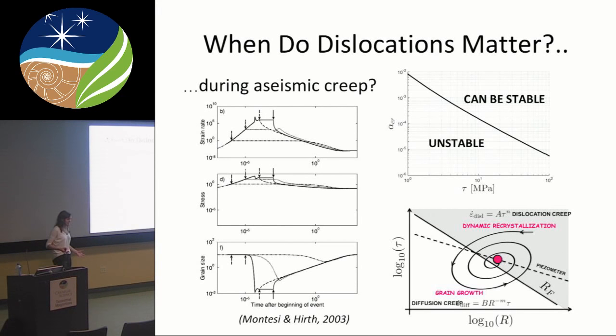So geological settings with this kind of physics could be important is, for example, a case of aseismic creep. So the scenario we're envisioning, if you have a sort of large earthquake, so stress, again, needs to be quite high in order for dislocations to matter. So you have an event that can be up to 100, maybe several hundred megapascals of stress. So say high strain rate, this is what's illustrated in this other study here, strain rate, stress, and grain size. So if you have an event where you have a pulse of high strain rate and high stress associated with it, you rapidly grind your grain size down.